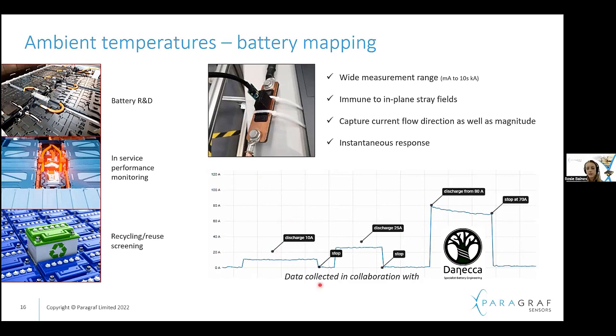And this data just shows the kind of response that we see. So we can see that during the discharge at a certain current, that's being measured and picked up by the Hall sensor with a very fast response when that is switched off, and a very clear response between the different currents as well. So a very accurate and very fast measurement of the current flow.